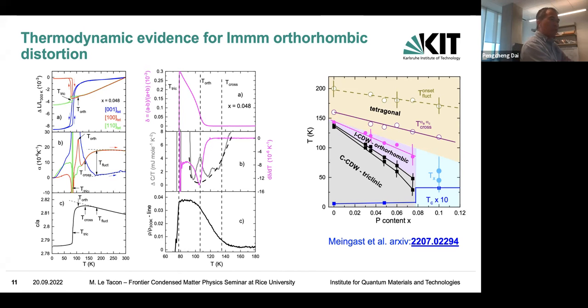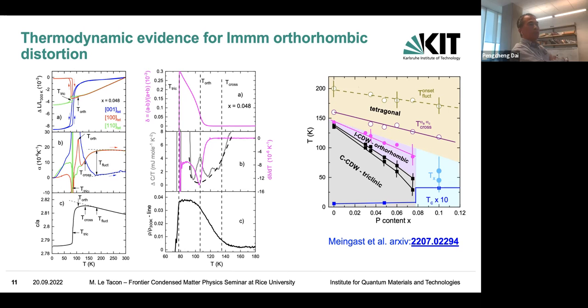Do you have anything to say about this? There's clearly a Tc enhancement around 0.1. So do you have anything to say about nematic fluctuations versus Tc, Jean-Pierre's claim? Not really, because I simply haven't really looked seriously at the superconducting phase. To me, this is too low a Tc, and I got turned on with this charge density wave story, and really, I wouldn't speculate.